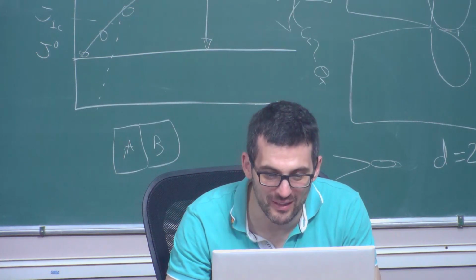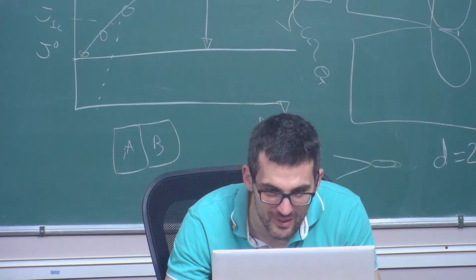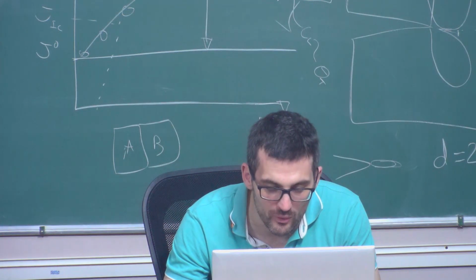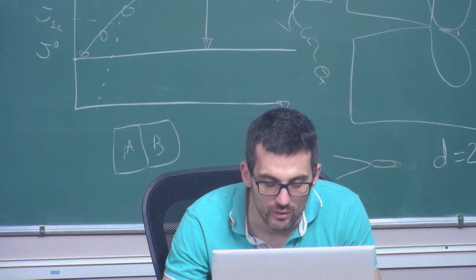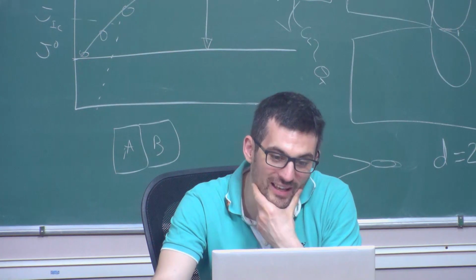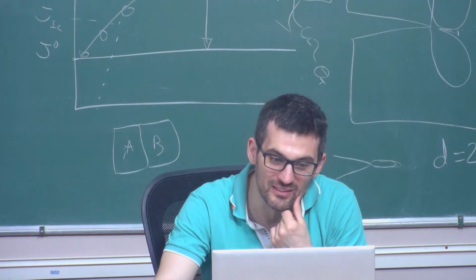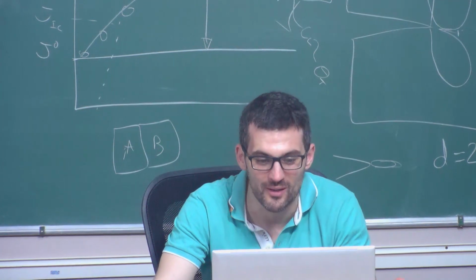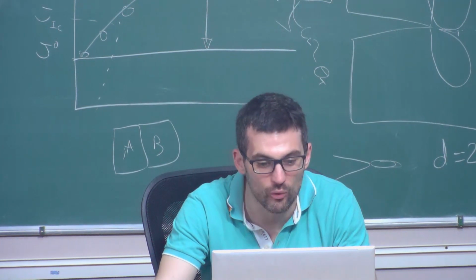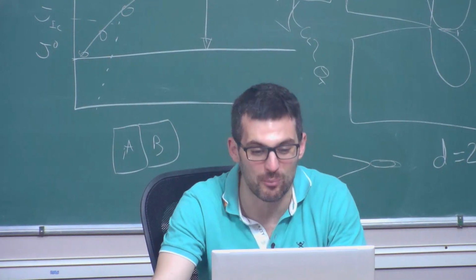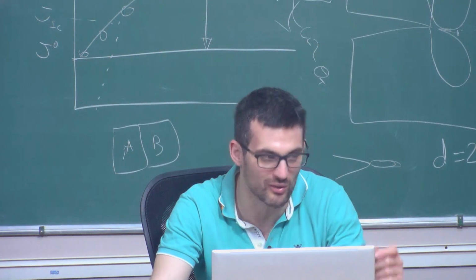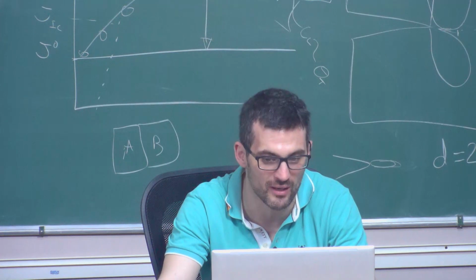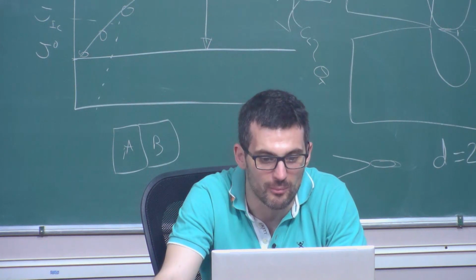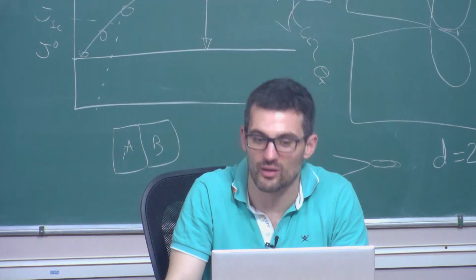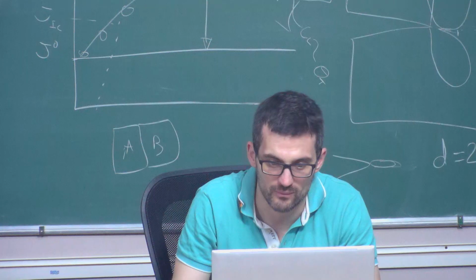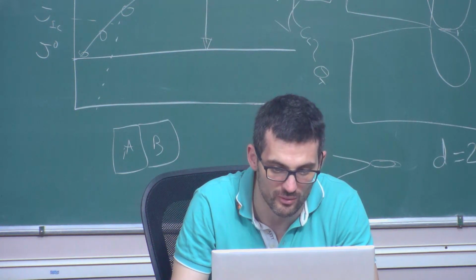And there's a question: how can we decouple strain localization effects from true hydrogen distribution in SSRT when multiple mechanisms exist? What do we say about the dominant failure mode? Well, I guess the last example that we did is the most relevant one, right? People did experiments under very low cryogenic conditions, and in this way you can decouple these phenomena. You can also do it by playing with strain rates, but at low cryogenic conditions you can decouple these phenomena, and we saw that eventually it was all driven by embrittlement. Anyway, strain localization without hydrogen will not drive intergranular cracking, as we saw later. But thank you for your question.